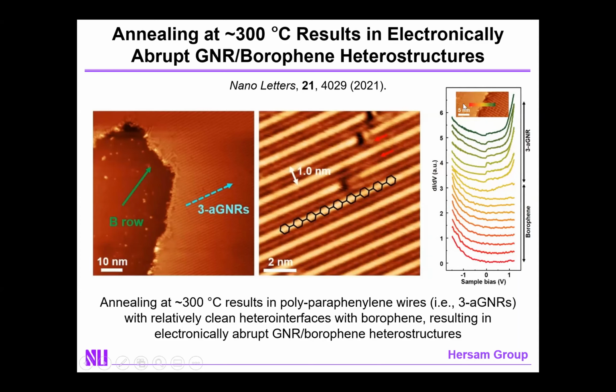And again, if we now take scanning tunneling spectra across the heterointerface, we see over the length scale of less than 1 nanometer a transition from the metallic borophene electronic structure to the semiconducting structure of the graphene nanoribbons. So again, we see this very abrupt electronic transition, not evidence for the more traditional Schottky-like depletion layers that are formed in conventional bulk semiconductor-metal heterojunctions, and suggests that something special is happening here in the two-dimensional limit.